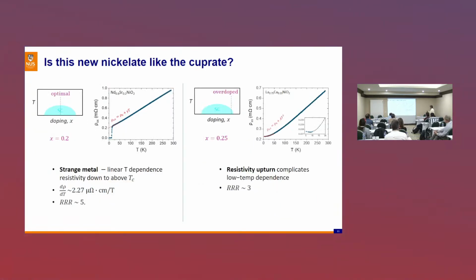So if we look at the resistivity behavior, this is in the case of the optimally doped. It shows this strange metal behavior, linear in T dependence, like what we have also in the cuprate. But if we look into the overdoped regime, it's a bit more complicated. Within particular regimes, which I don't show here, you can fit with a different temperature dependence. But dominantly, as you can see here, at very low temperature you have this upturn, which is different from what we have in the case of cuprate.